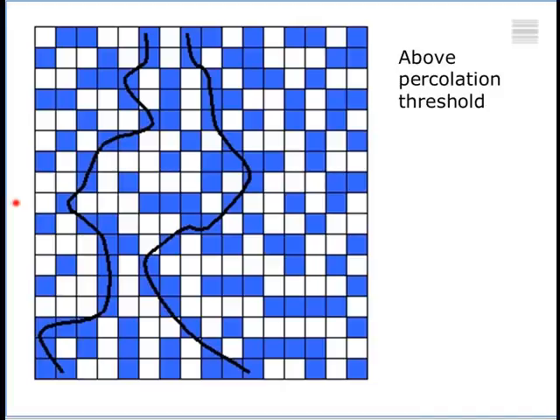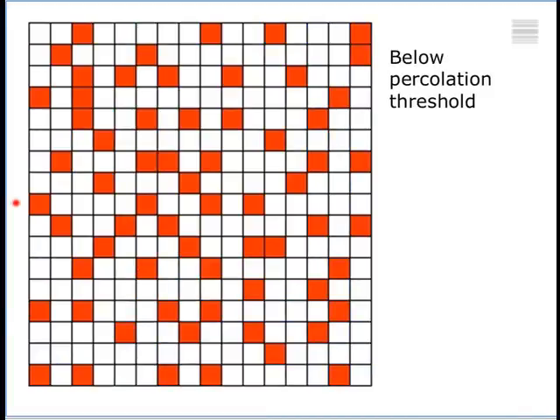On the other hand, as deformation proceeds, the amount of austenite will decrease, and eventually we will not be able to draw a continuous line through the structure. So here is the red austenite, now has lost percolation because there's no way I can draw a continuous line through the austenite. So then you are stressing the less ductile phases, okay, and fracture happens. When we do a calculation, we find that the percolation threshold, that means the point where you can no longer have continuity through the austenite, is about 10% of austenite.